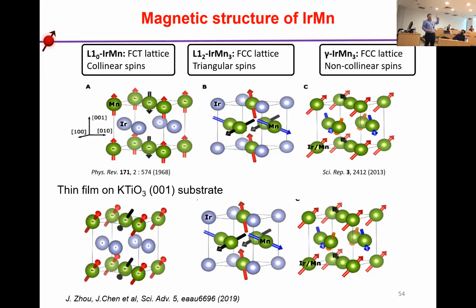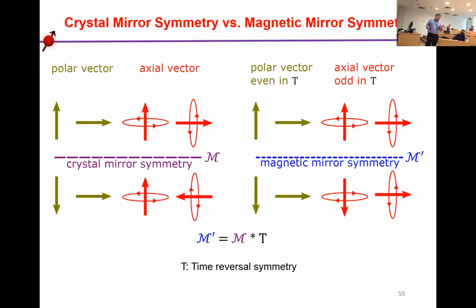from the perpendicular direction to the 1-1 directions. So the Néel vector is along the 1-1 directions. But for the L12 and the gamma phase, it does not change. But when we introduce the magnetic mirror symmetry.